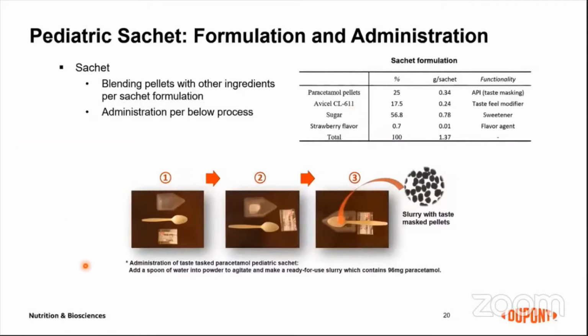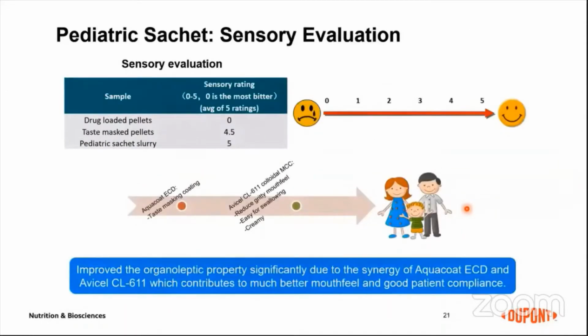So actually the administration process is very simple. Just add a spoon of water into the dry powder, then agitate to make a ready-for-use slurry, right? So inside of this slurry, there are numerous taste-masked pellets. And then we can see the sensory evaluation results for this pediatric sachet. Compared with the uncoated drug-loaded pellets, the taste-masked pellets and the pediatric sachet slurry have much better sensory rating, in particular the pediatric sachet slurry, because we also add sweeteners and flavor.